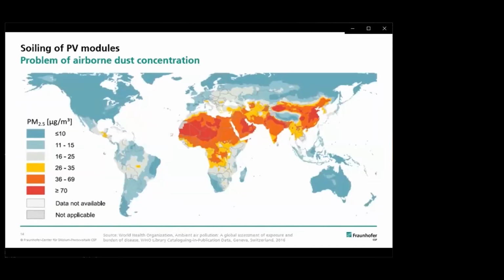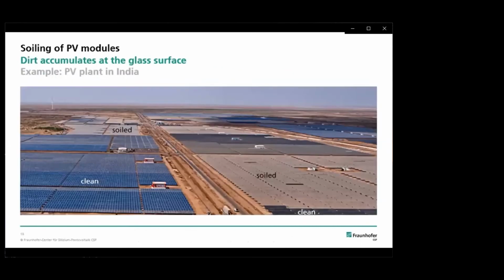But to put it more into numbers, here you can see the average annual airborne dust concentration, which is especially high in the so-called global dust belt, reaching from North Africa over the Arabian Peninsula to India and China. As a result of high airborne dust concentration, dirt accumulates at the glass surface, blocking the sunlight and significantly reducing the power output up to 70% or even more. In the photograph, you can see an example of a PV plant in India, which got heavily soiled and partly cleaned.